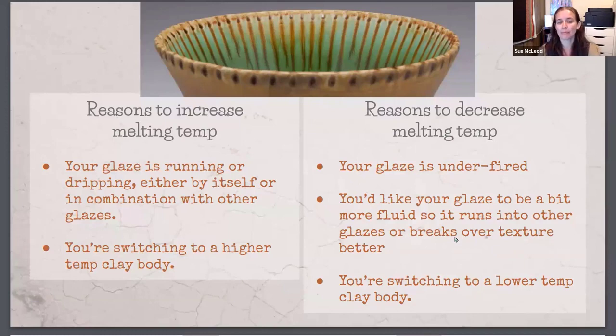Or you want your glaze to break over texture. So you might create a lot of texture in your pieces, and then you put a glaze on and it kind of just covers everything up. That's usually to do with the melted viscosity of your glaze in the kiln. And if you lower the melted viscosity by lowering the alumina level, then that will help you create a glaze that is more fluid and will sink into the low spots of the texture and really highlight the texture on your pieces. Or if you're switching to a lower temperature clay body, then you need to lower the melting temperature of your glazes.